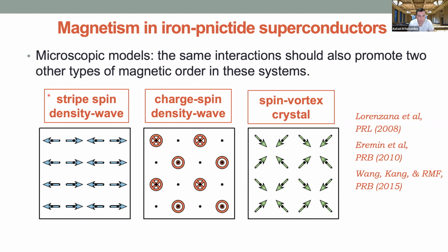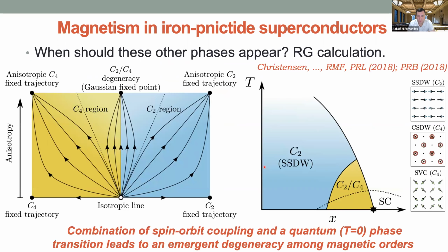You can ask, how do I decide between these three phases? What you found out when you did the renormalization group calculation is that when you combine spin-orbit coupling, in proximity to a quantum phase transition, you find that the degeneracy gets extended, an enhanced symmetry, a closer degeneracy between these different phases. So the expectation is that as you approach this quantum phase transition, these other phases, the charge-spin density wave or spin vortex crystal, should start appearing.